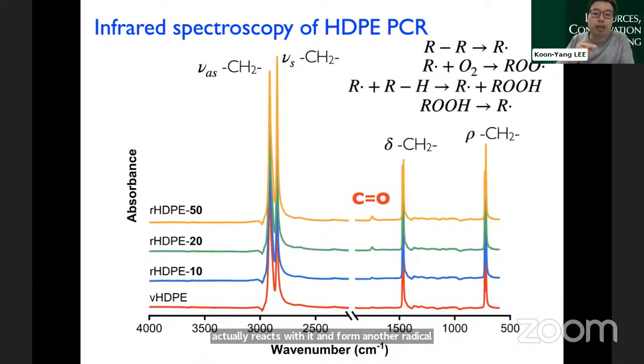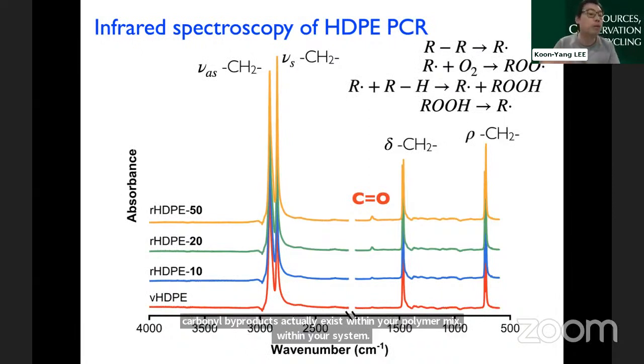And all of these radicals will actually react again with the polymer, with the carbon-hydrogen bonds in the system, forming more and more radicals, forming more and more carbonyl groups. And the worst thing is that these things are self-propagating. So the more you run through at high temperature in the presence of oxygen, the more of these carbonyl byproducts actually exist within your polymer mix, within your system. So is it a good thing? Is it a bad thing? So this is actually what we'll investigate today.